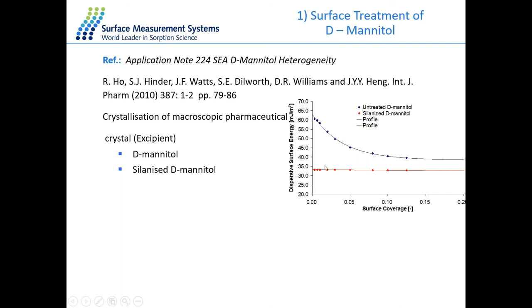And in case of the silanized D-mannitol, which is the red line here, this time, as you can see, the energy on the surface is almost the same level. All the sites on the silanized D-mannitol become the same level of energy because of the same functional group on the surface. That means after silanization, the surface energy becomes lower compared to the untreated mannitol, and the sample becomes more homogeneous and more uniform with the silanization process.